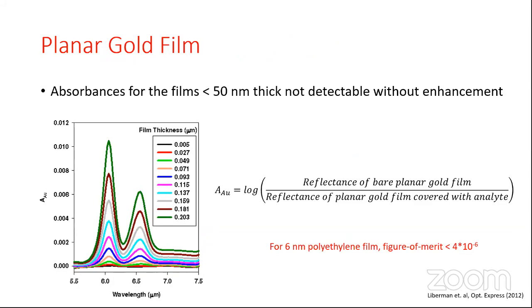Let's start with the planar gold film. The image was taken from the literature that I got the figure of merit from. As you could see, for films less than 50 nanometer thick, no detectable enhancement was shown. And again, the number we're interested in is the logarithm of the ratio of reflectance of bare planar gold film divided by reflectance of planar gold film covered with analyte. And I actually did the simulation studies, and I saw a figure of merit of less than 4 times 10 to the minus 6.